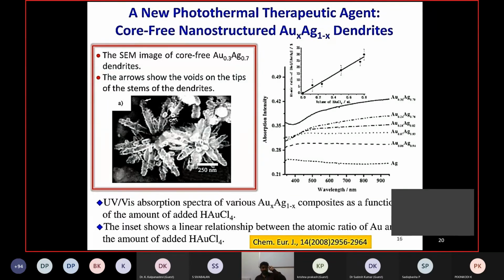Here is one example where you use a silver gold alloy. These are observed as dendrites. They are formed in dendritic forms. The advantage of forming dendrites is one thing that I explained in the last lecture. If they are non-spherical, they have a longer circulation time. So such non-spherical structures with larger aspect ratio are more interesting. And another interesting property is that they have a broad absorption. What is the advantage of having large absorption? A long range of absorption starting from 500 even up to 1000. See the broad absorption band. What is the advantage of that?